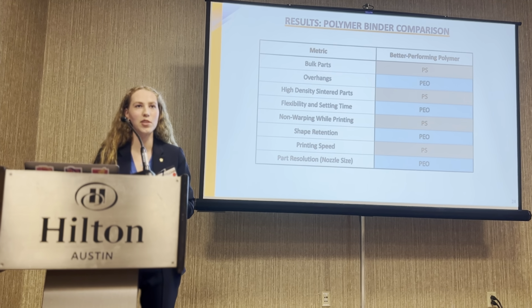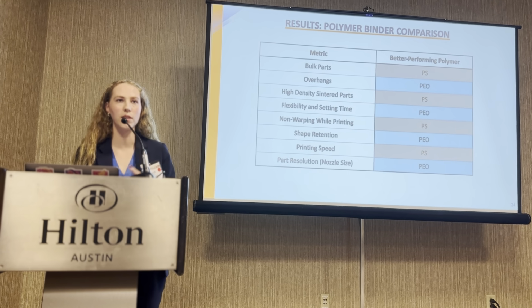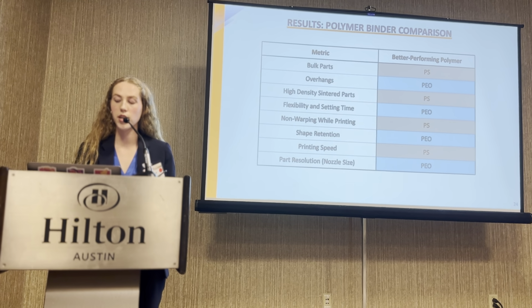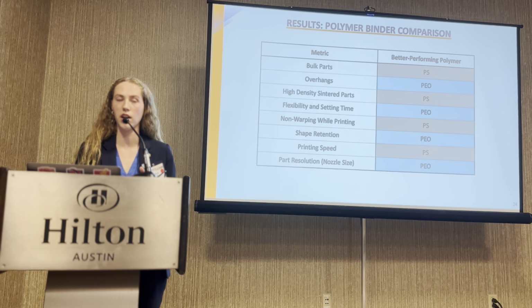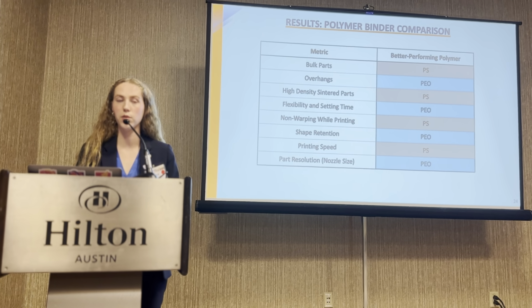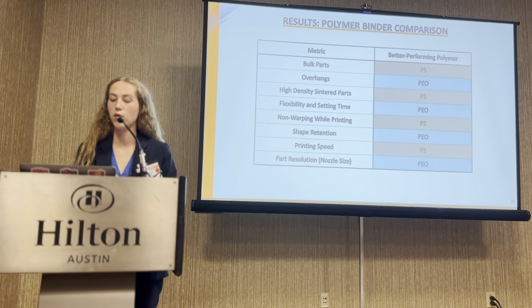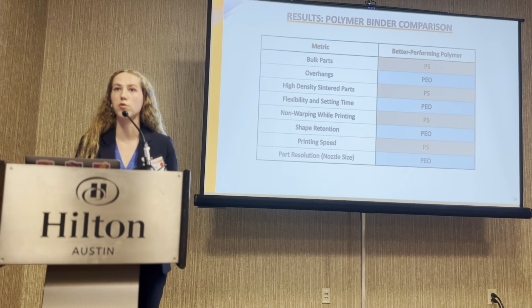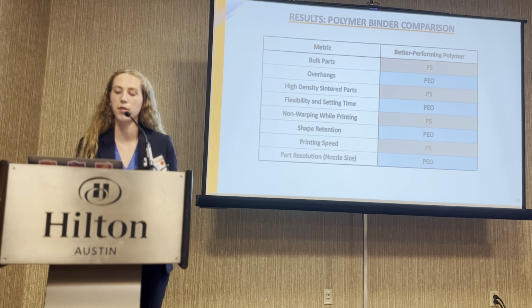So to recap, for the differences between our polystyrene and polyethylene oxide, polystyrene is much more preferable for bulk parts and high density parts, but the PEO is preferable for shaping parts, overhangs, and shape retention when sintering, which are some crucial elements of this origami method.